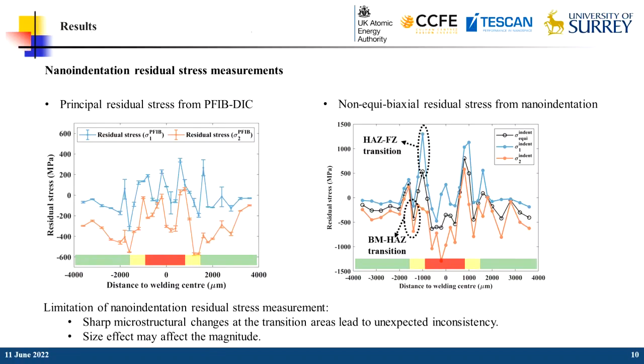On the left, it is the distribution of the two principal residual stress components derived from the PFIB-DIC method, where you can see the peak values at the interface. On the right, it is the distribution of the two principal residual stress components measured using the nano-indentation, where the equal biaxial residual stress was transformed to the non-equal biaxial residual stress by the location-dependent stress ratio K. Both figures display similar trends, although the peak values at the interface show some level of disagreement regarding the magnitudes.